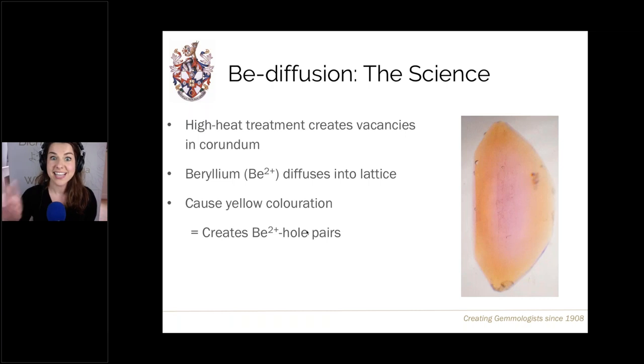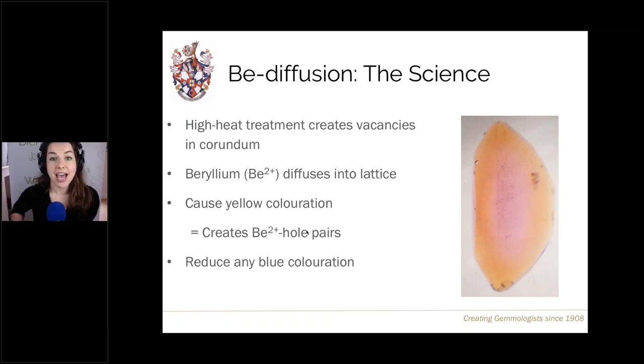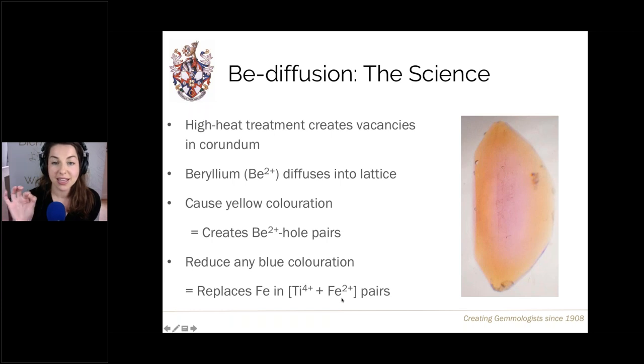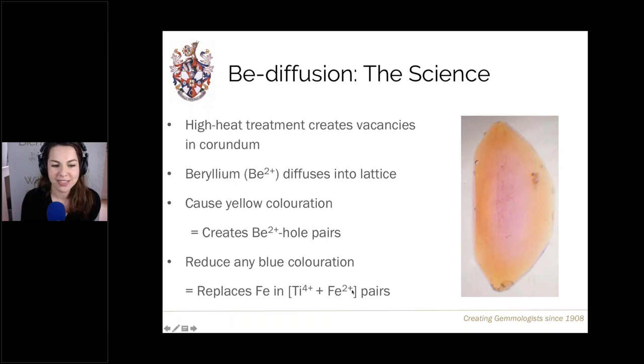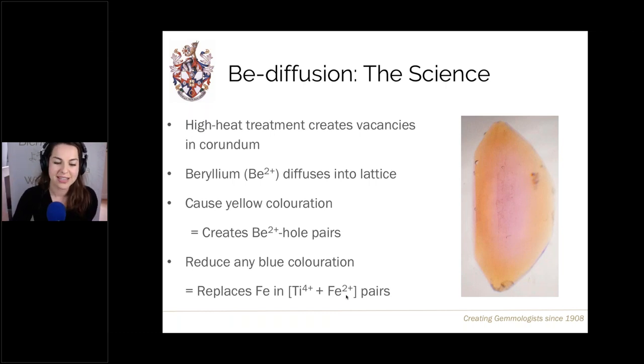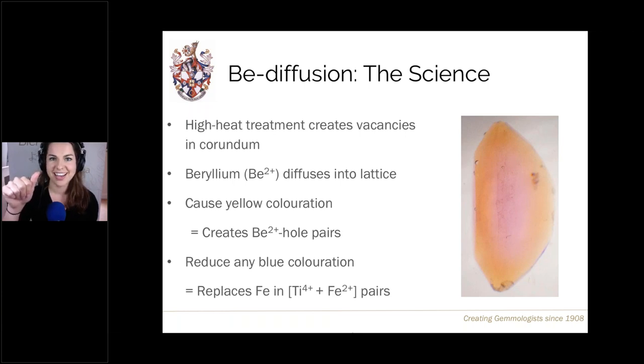The second thing beryllium does is reduce the blue colouration in these stones by replacing iron within iron-and-titanium pairs. Titanium and iron together (Fe²⁺ paired with Ti) is the colour mechanism for blue within sapphire. Because Be²⁺ can easily be substituted for Fe²⁺, those pairs are broken — that blue mechanism is destroyed — so Ti-Be pairs do not cause blue, resulting in an overall reduction of blue colour. In summary, beryllium causes yellow through trapped hole colour centres and, if titanium-iron pairs are present, reduces their number and thereby reduces blue colour.